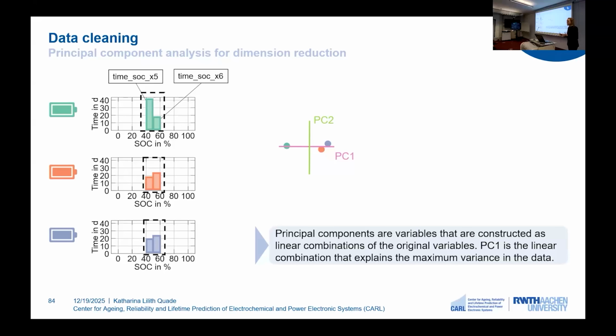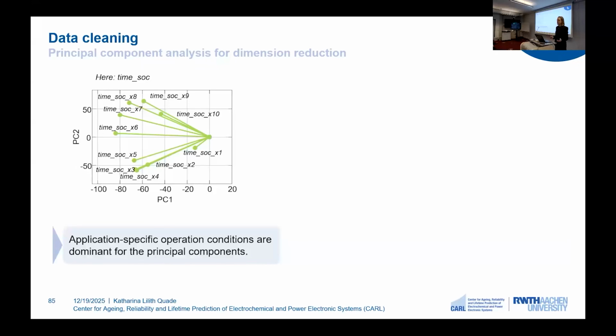However, our use case is more complex. We have for this variable 10 bins, not 2 bins, and we also have 600,000 vehicles, so not only 3 vehicles. And now we apply PCA to all of our data, and we get the resulting so-called loading plot. The loading plot for the time SoC now describes the different contributions of the single variables to our principal component. And we can see that, for example, the highest loading is for when we focus on PC1 for time SoC X6 and time SoC X7. And this makes total sense because these conditions are the most prominent in our use case.